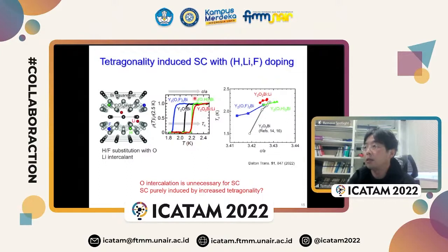This is not oxygen intercalation, but lithium intercalation or fluorine or hydrogen doping. And actually, we can obtain a higher superconducting transition temperature in the case of lithium intercalation or hydrogen doping. So in this compound, the oxygen intercalation is not a necessary factor for the emergence of superconductivity. And still this tetragonality dependence seems to apply for the emergence of the superconductivity. All these results are experiments on the bulk polycrystal.